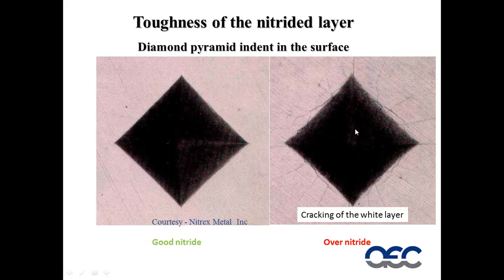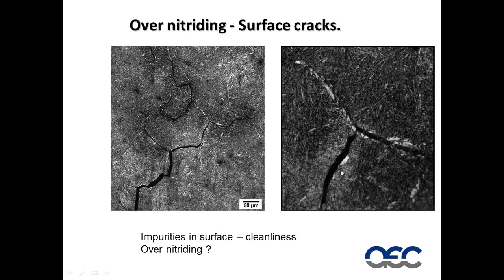In this case, there is this very, very hard, glassy layer in the surface known as the white layer or the compound layer. This has cracked, and you can see all these micro cracks coming out from the indenter. This is not good. This means that the surface is brittle and prone to damage. And on a larger scale, if we look at the surface of the steel, it can start looking like this.